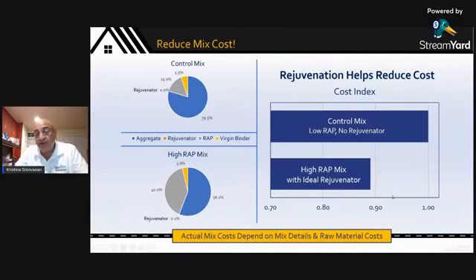12% lower. So not only are you able to get good properties out of this rejuvenator, not only is this rejuvenator able to provide those continuing good properties over a long period of time, you're also able to reduce the cost of the mix. And you do this because you force more and more of the aged bitumen in the RAP to contribute meaningfully as a virgin bitumen. And that's the other real driver for this.